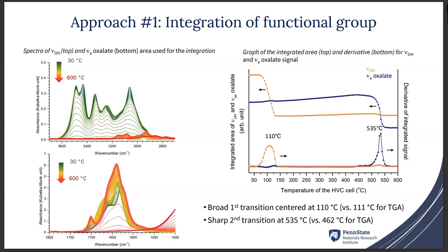If we follow this integration over the range of temperature we set for the cell, we see that for the hydroxyl, when we plot the derivative, we have a maximum at 110 degrees Celsius compared to the 111 given by the TGA. When we look at the asymmetric stretching of the oxalate, we see a change at 535 degrees centigrade, which was supposed to happen at 462. So we can already see a huge disparity between the temperature we set and the actual temperature of decomposition we are probing by FTIR.